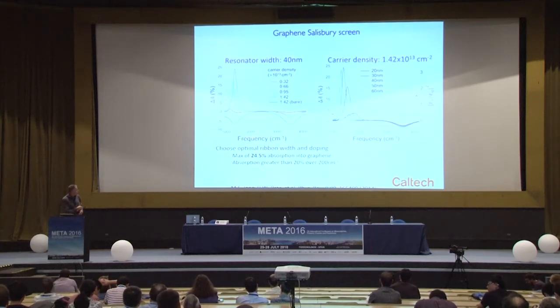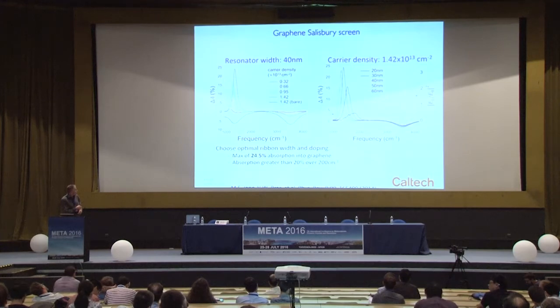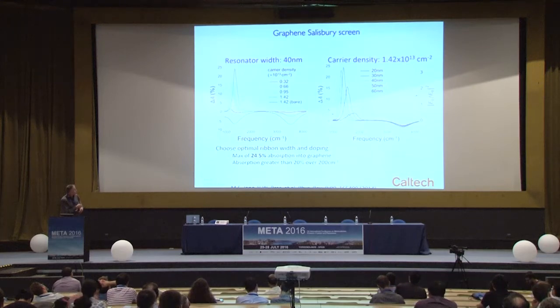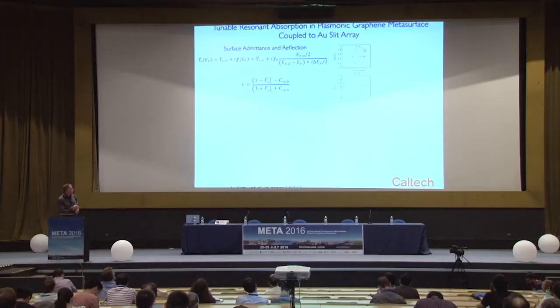And when we vary the carrier density to tune through the graphene resonance, we can see that the absorption rises from the 2.3% value characteristic of single pass transmission to strongly resonant absorption here, almost as high as 25%. So we can tune entirely through this line width and see a significant increase in the interaction with even a single monolayer of graphene. And a way to think about this is that essentially what we're doing is impedance or admittance matching the graphene to free space. This was the insight that was first recognized by Salisbury.